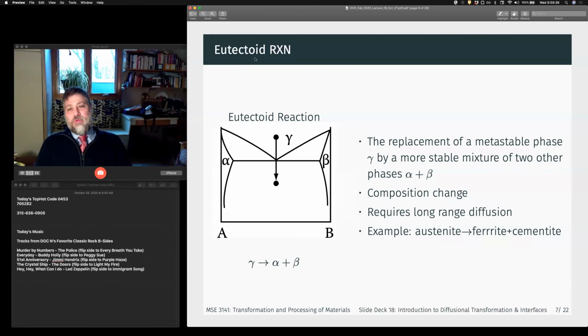the next really important diffusional transformation is eutectoid reaction. So we start up here in the full gamma regime and quench down. So here now we have metastable gamma going to alpha plus beta rather than alpha prime going to alpha plus beta that we would have over here, right? So again, this requires a composition change, requires long-range diffusion, and it's quenchable, right? And it's going to depend on the cooling rate. So we'll see that the rate at which we cool down and the rate at which we quench is going to give us different microstructures, right?